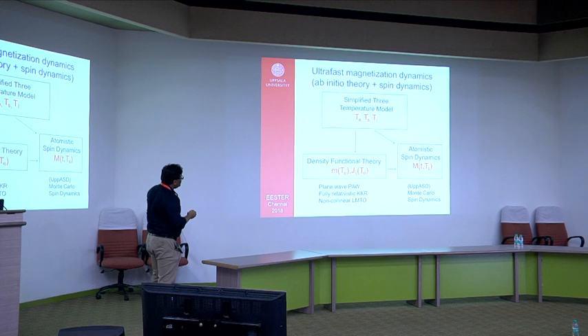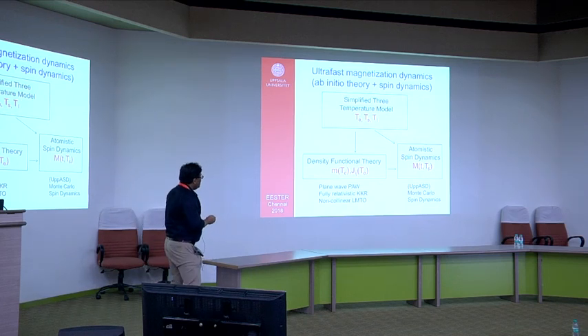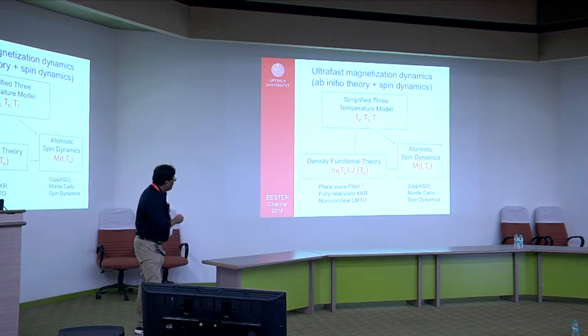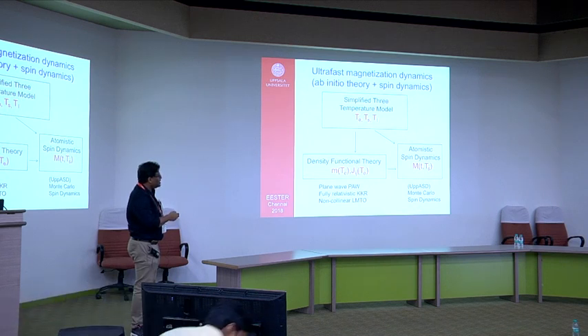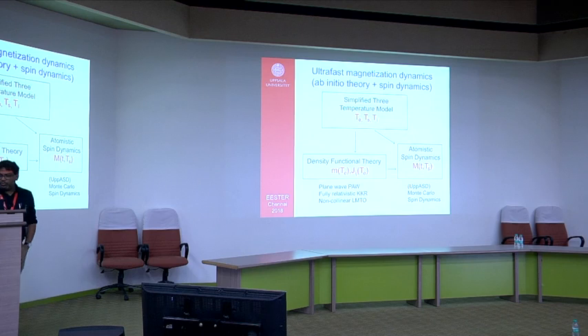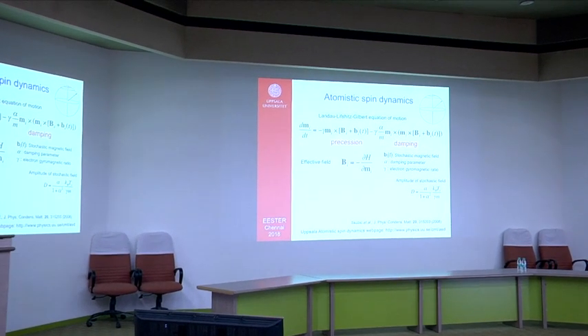The electron temperature is passed to density functional theory. That means we calculate the static properties as a function of electron temperature. I'm talking about temperature-dependent things one can do in DFT with a Fermi-Dirac distribution function. Anybody of you can do it. So, magnetic moment as a function of electron temperature, and the exchange parameters as a function of electron temperature. Also, the spin temperature is passed to the atomistic spin dynamics simulations, where the magnetization is calculated as a function of time and also as a function of spin temperature. This part we can understand a little bit, but what is this part? Atomistic spin dynamics. I want to show you that, and then most probably I have to finish.